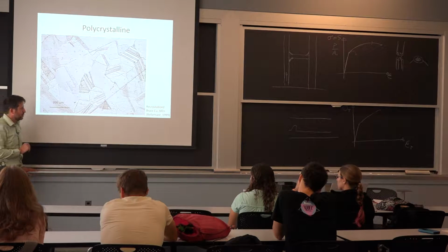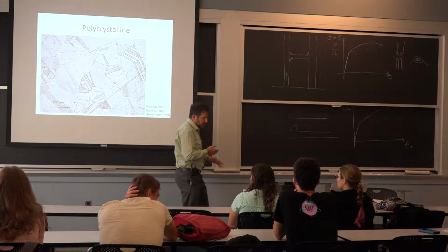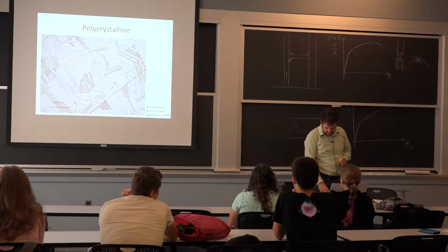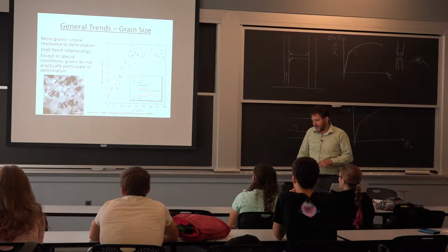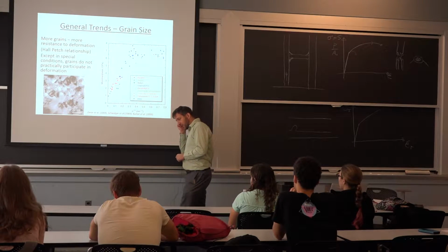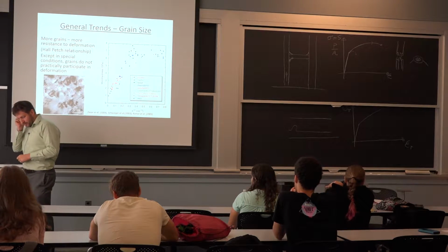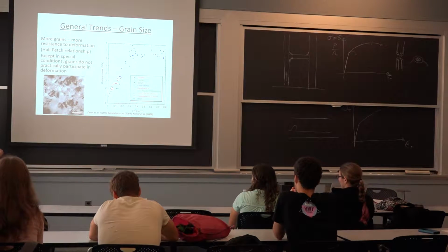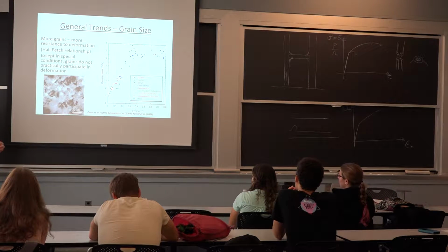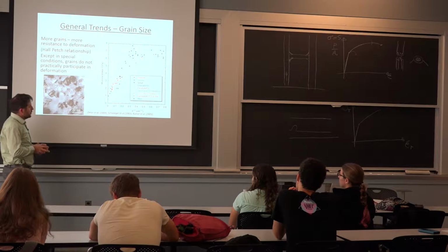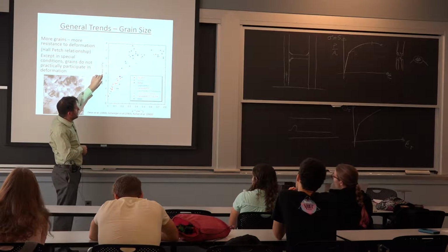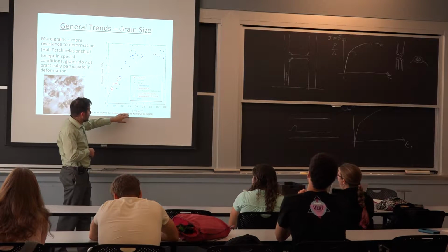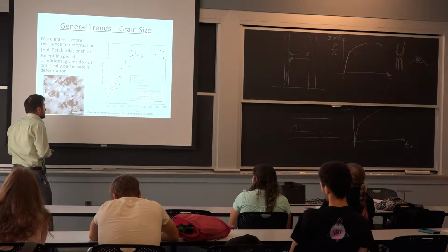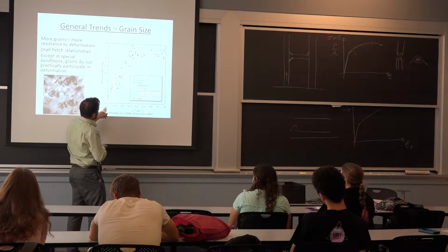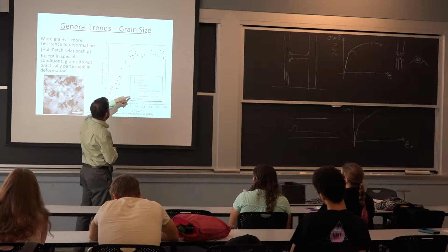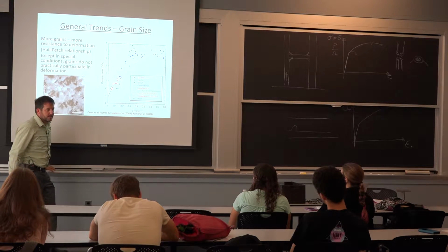It's actually an advantage, and we'll go through that as we move forward. So the grains typically affect a lot the strength of the steel or the metal, or the material that you're dealing with. Here, what we have is the hardness of certain metals as a function of the inverse of the diameter of the grain. So essentially, the grains are getting smaller going in this direction, and they're getting into the nanometer range.